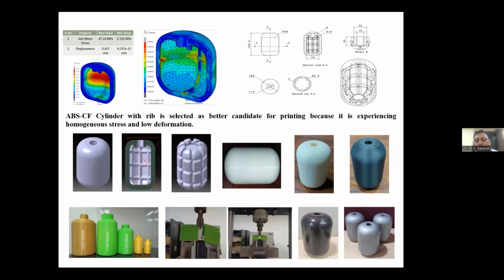At the bottom right-hand side, you see two different cylinders coated with some colors, and these are specifically coated with thin layers of metallic particles, especially nickel and copper. When you look at these coatings, you may wonder why we need them when carbon fiber is already present as a supporting and strength-enhancing material. As we are 3D printing these cylinders, however small the layers are optimized, there are minute micropores present between the two layers that are printed during the process of 3D printing.